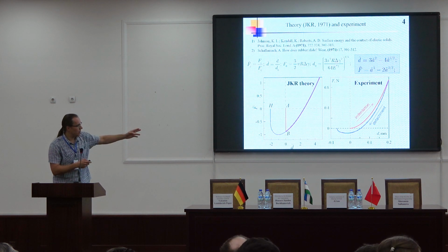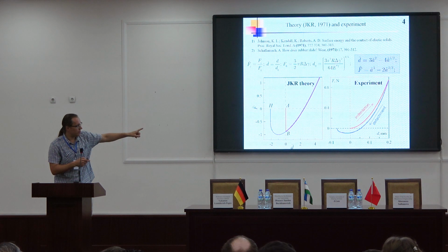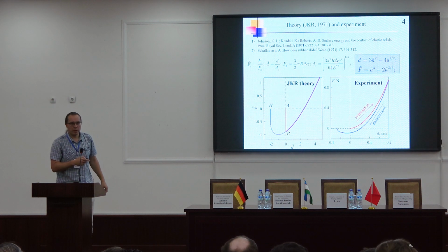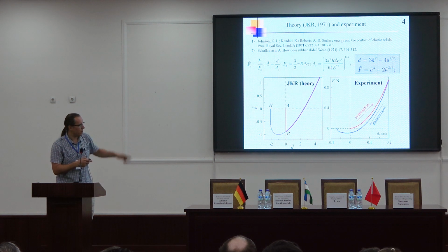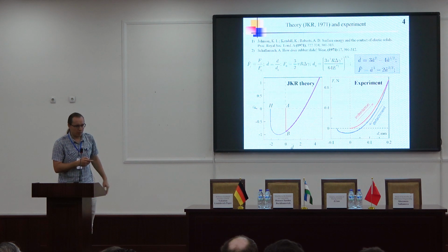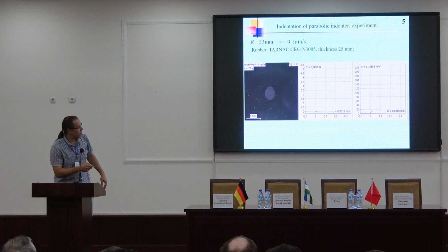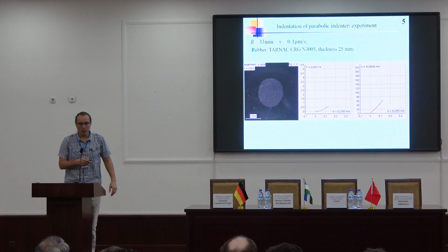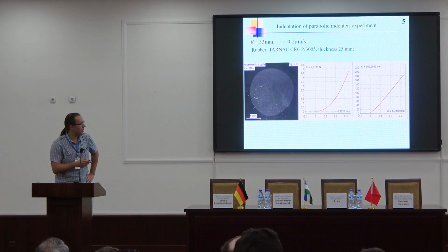During this indentation, the action of adhesion is very low. We also observed negative normal force at this first contact point, but it's a very small normal force, and at detachment you can see this adhesive force is much larger, with negative values due to adhesion. And here is also a video of one experiment for normal contact, in indentation and in detachment.